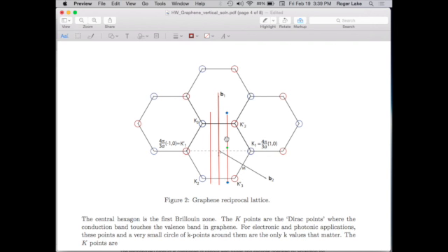If you roll it up, so it's going to be just a PZ orbital, PZ bonding again? Okay, if you make the circumference really tiny, then you start getting matrix elements between the PX, PY, and the PZ. And you start getting hybridization, and that changes the picture. Once you start getting diameters below a nanometer, and as you get really tiny, then you have to really worry about the other orbitals.